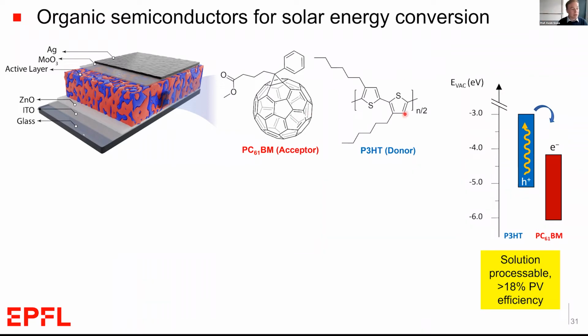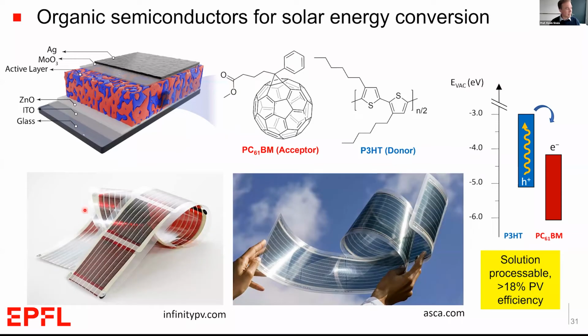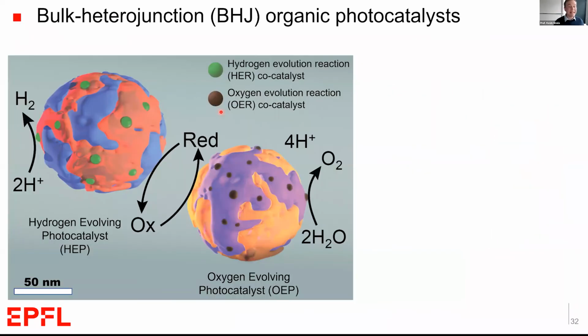And because these materials can be dissolved into the same solvent and cast into a single film, this heterojunction can be formed really on that nanometer length scale. And this concept has been quite successful for photovoltaic devices, especially these solution-processed ones, which are now in competition with the perovskite type cells. But what really interests me about this is the fact that potentially we can figure out how to use this concept in a bulk heterojunction photocatalyst.